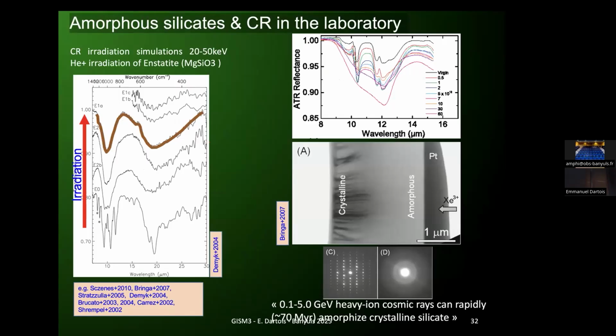Experimentally, this has been demonstrated: if you start with a crystalline silicate and irradiate it, here with something rather low energy, helium plus, but still in the electronic regime of the interaction, starting from enstatite, you see that after some time of irradiation you get something initially with a lot of structure, as would be crystalline silicate, and then you lose the structure and get something amorphous that resembles what you can have in space. There have been other experiments on other crystalline silicates and different energies, and to make a long story short, with 0.1 to 5 GeV cosmic rays, you can amorphize crystalline silicate in the diffuse medium within a few tens of millions of years. So it's an easy explanation for the fact that you are seeing them as fully amorphous in the diffuse medium.